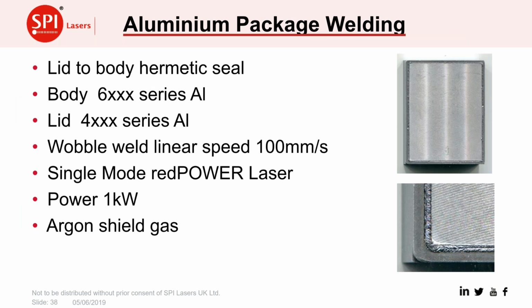And just looking at how that might work out in practice, I said at the beginning that one of the things was you often end up welding up packages where you've got to control the heat because of something inside the package. So this is looking at an oscillation weld doing a hermetic seal around the aluminium package, where we've managed to produce welds between different types of aluminium and produce a hermetic seal at a good speed and giving a good quality. And actually there was a low heat input for this.